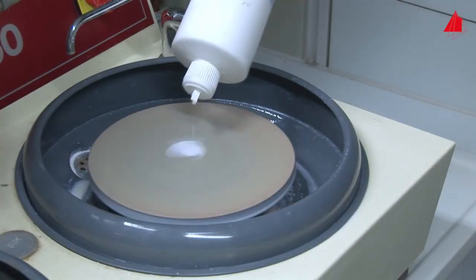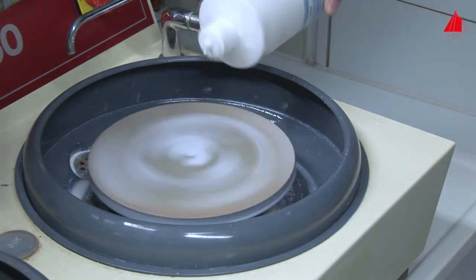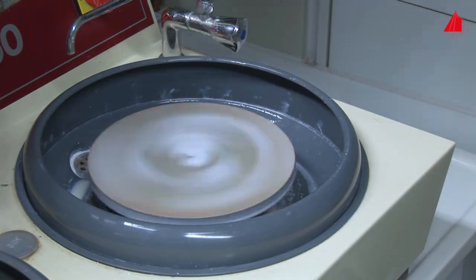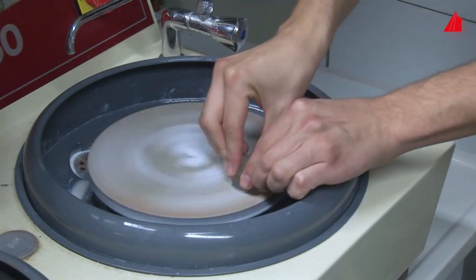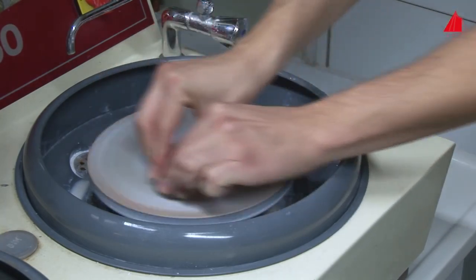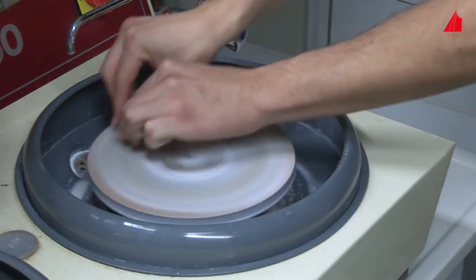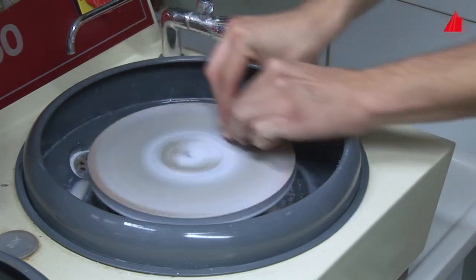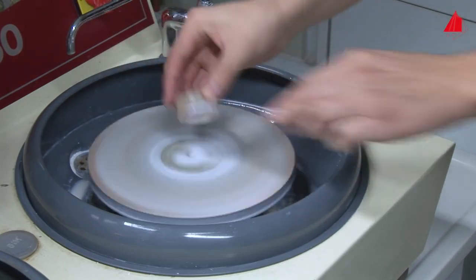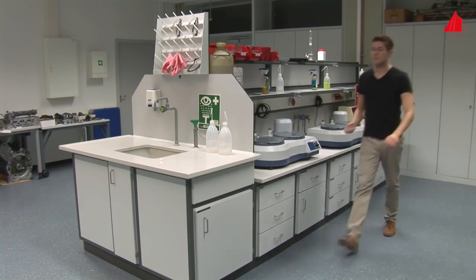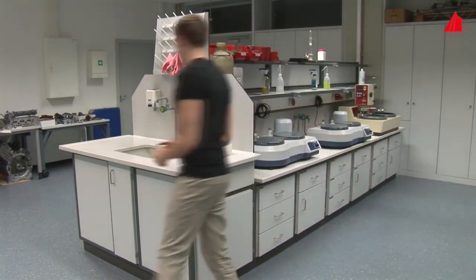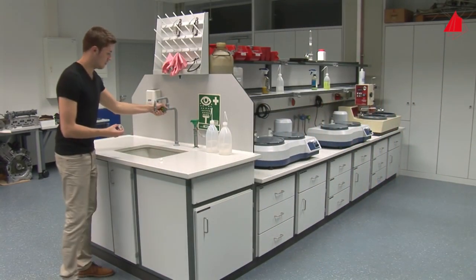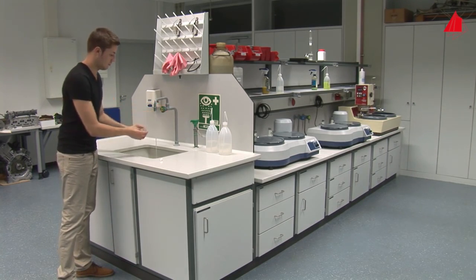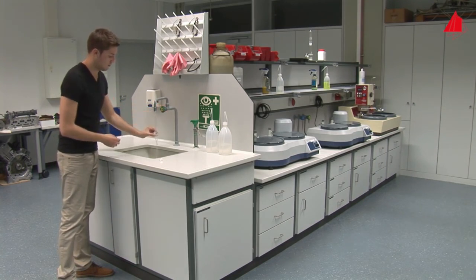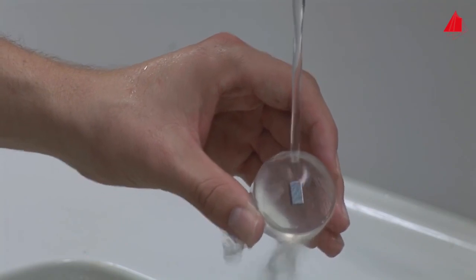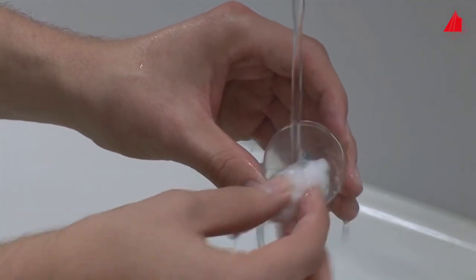Nevertheless, the specimen has to be cleaned again and go through a third and final polishing operation. This time, 50 nanometer aluminium oxide abrasive is used. Only then is the surface prepared to a sufficient quality. At the end of the mechanical preparation, special care has to be taken to clean the specimen properly. On the one hand, all abrasive particles have to be removed. On the other hand, the freshly polished surface must not be scratched or damaged.